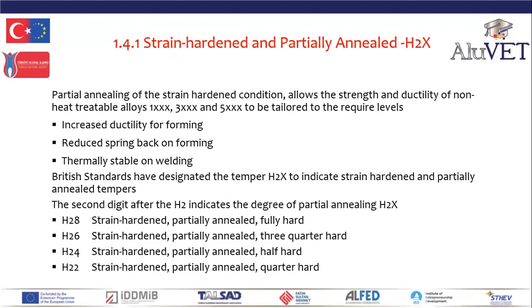So partial annealing of the strain-hardened conditions allows the strength and ductility of non-heat treatable alloys, the 1, 3, and 5000 series, to be tailored to the required levels. We can balance strength with increased ductility for forming. Partial annealing reduces the spring back on forming, so enables accurate forming. Partially annealed aluminium is thermally more stable, so it will not recrystallize in an uncontrolled manner.